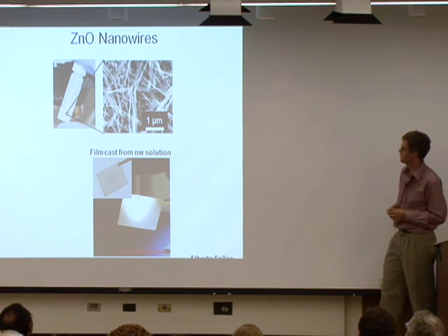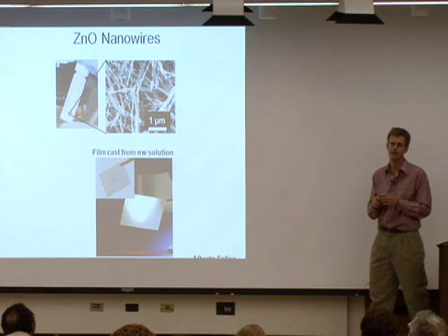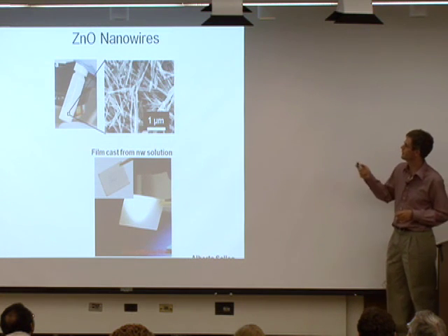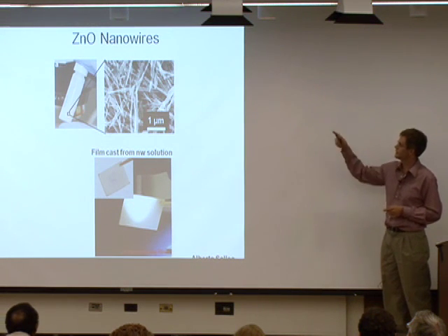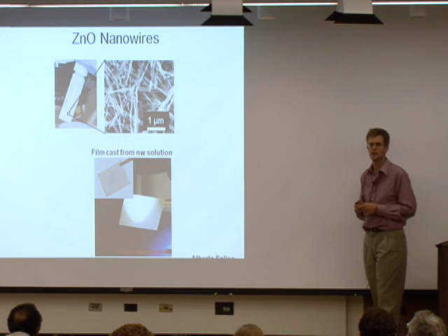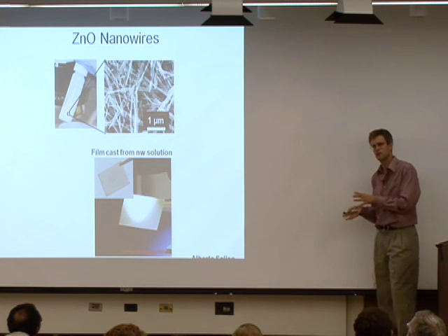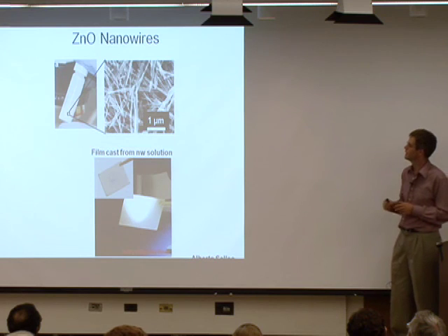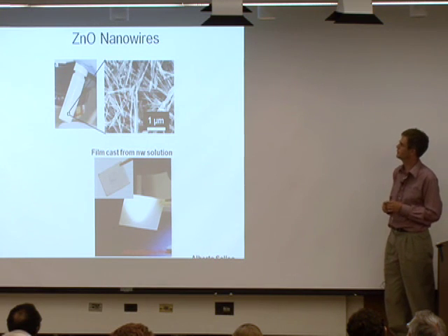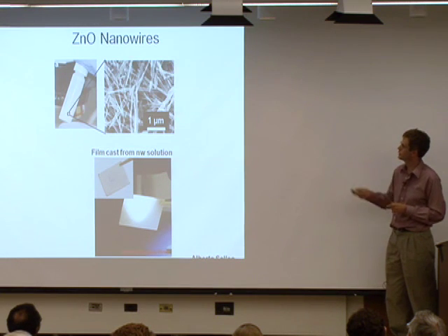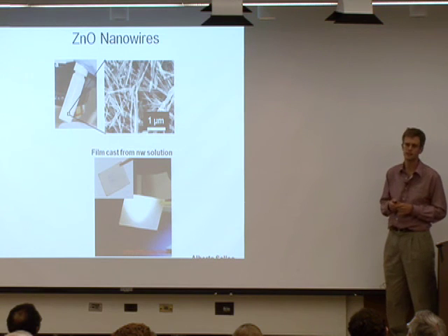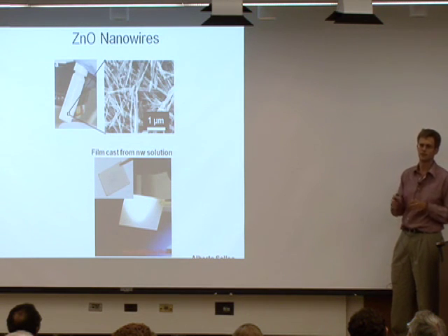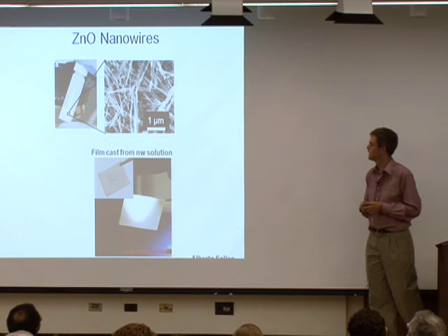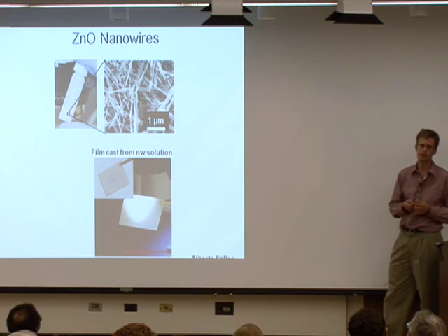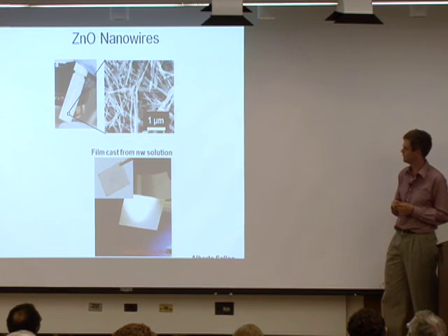And Alberto Salleo has a third twist on this. He's using zinc oxide nanowires. Zinc oxide is inherently transparent. It doesn't conduct as well as silver, but it's much more transparent. And so this could possibly be the way to go. Currently, these films are a little bit more resistive, but the work is still in the very early stages. And the doping level, for example, has not been optimized yet.